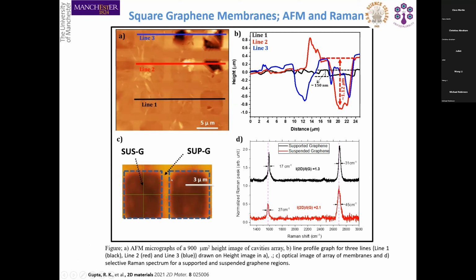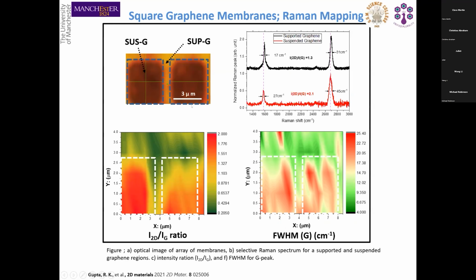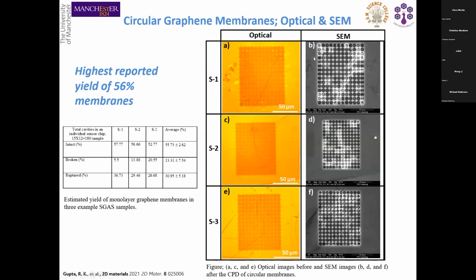So it's very important to understand what happens when the graphene is freestanding, without the surface, because then you do not have unwanted doping from the surface or any scattering that comes from surface contamination. This is further Raman spectroscopy just to show that we have a good area of suspended graphene compared to supported graphene.